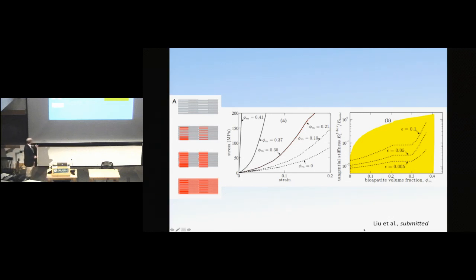And we see in these plots, these are stress-strain curves that we try to predict, and this is the stress-strain curve that was input data. This was the model from the Buehler lab, from that molecular atomistic type model. And there's a fairly mild stiffening that occurs with this model as mineral accumulates on the inside of these gap channels.